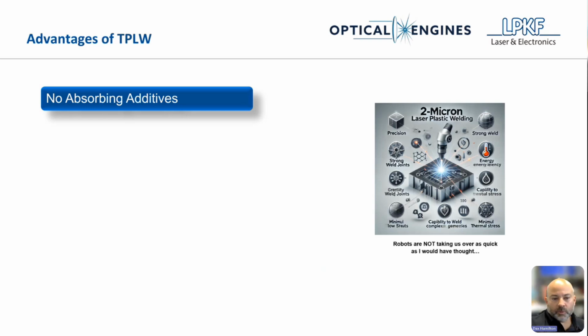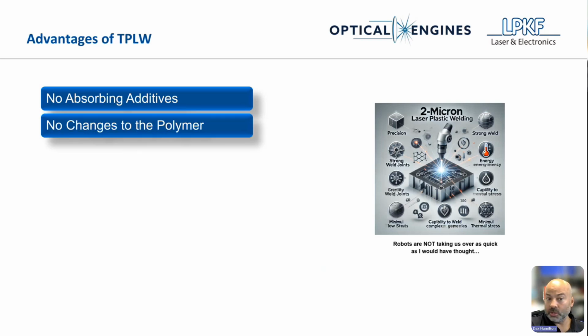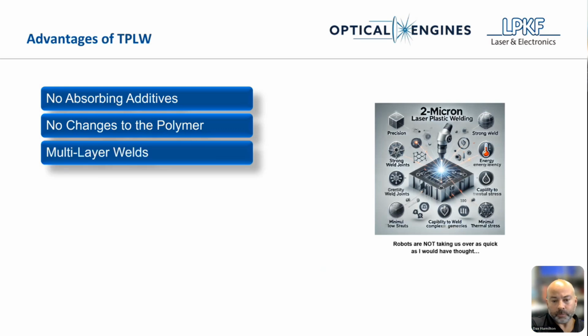So advantages of transparent polymer laser welding: no absorbing additives needed. So you don't need any sort of, I think it's green and blue, different IR absorbing chemicals in the plastics. You don't have to change the base polymer at all, so you can keep it in its natural state. You can do multi-layer welds. So you could stack up, I think we've done 12 or 13 layers of films. And since it's volumetric absorption, the laser energy will travel all the way down through these different layers.